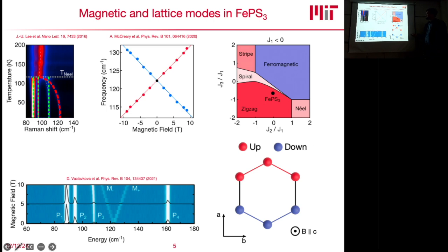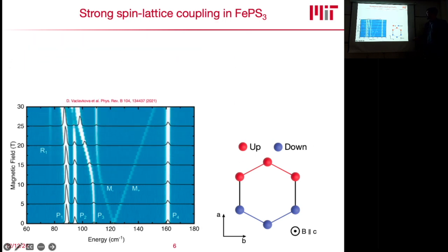People in the past have carried out these Raman-type measurements under this magnetic field, which is shown here. So you can very nicely see the splitting of this magnon mode. And the very interesting thing is, if you go to much higher magnetic field, you start seeing these avoided crossings here. So this here, P3, that's a phonon. And what an avoided crossing usually tells you is that two collective modes are strongly coupled to one another, which, since you see an avoided crossing here between the magnon and the phonon, means that the spin and lattice degrees of freedom in this material are very, very strongly coupled, because this splitting is actually pretty large.